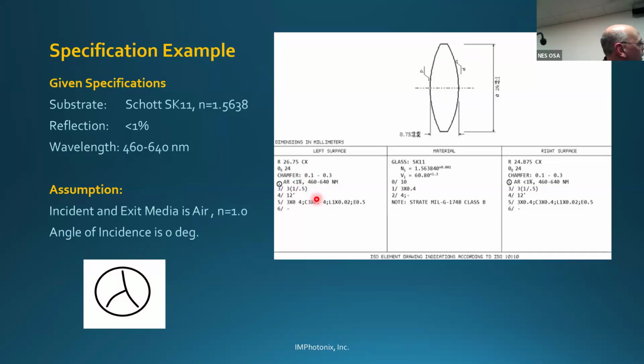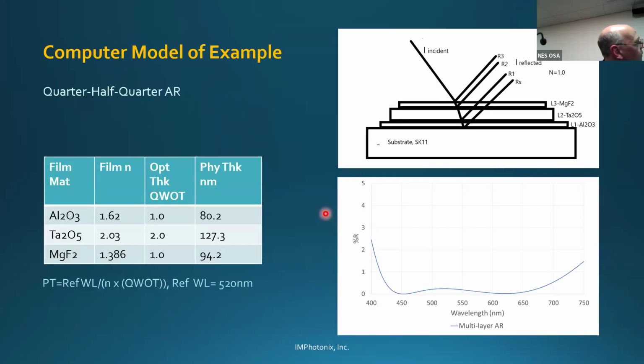In the case of this drawing, the lens is an SK11 with an index of 1.5638. The specification for the application is a reflection of less than 1% at a wavelength range of 460 to 640. Now, what we have to assume here, from a designer's point of view, is that the lens is operating in air, because that makes a difference in the design of the AR coating. So we assume that air is 1.0, and also that the angle of incidence is 0. As the angle changes, the reflections will change, and the design of the coating has to accommodate that.